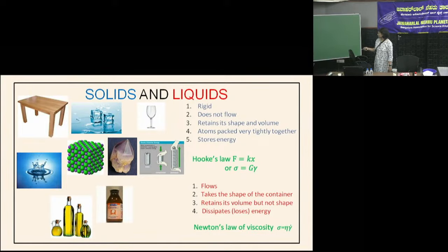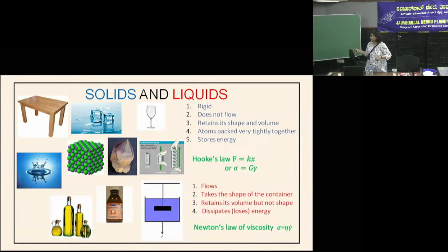In rheology we normally depict a liquid-like material with something like this, which is a dashpot. In the picture that you see here, the blue is a liquid, and you have a piston that is being driven through the liquid. As you drive the piston through the liquid, you are applying some mechanical energy, and that mechanical energy is immediately getting dissipated. How does the energy flow happen? As you are pushing the piston down, the molecules near the piston start reorienting, and they carry the mechanical energy that you've supplied to it during that reorientation process.